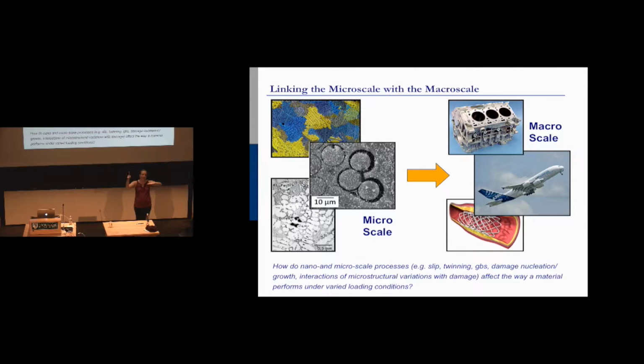And so what happens actually, and the reason that you see these stress life curves out to here, is because you're looking at 10 to the 6, 10 to the 7 cycles, and then usually the data stops. The reason for that is purely a practical one. If you take a specimen and you test it to 10 to the 9, 10 to the 10 cycles in a typical uniaxial test frame, let's say it can go 5 hertz, you'll be testing one sample for a year. There's no graduate student on Earth who is going to sign up for that project.